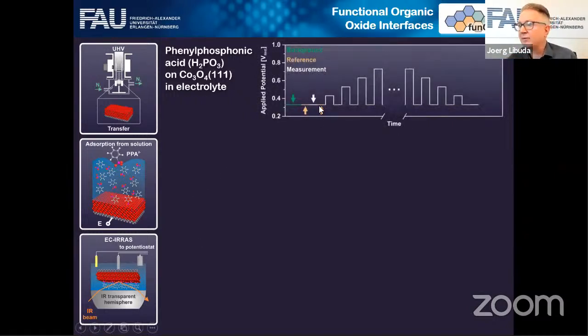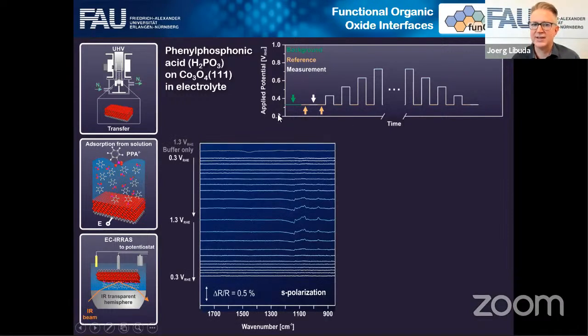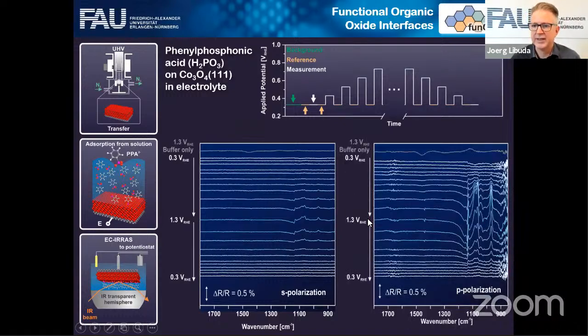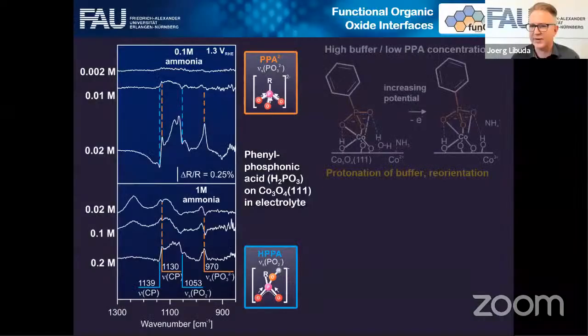And remember, infrared experiments are always difference experiments, as I said. So we have a reference potential. We jump to a different potential and go back and always do the steps and look at differences. And these are the difference spectra that you see in S-polarization. In S-polarization, you hardly see anything. It tells you that there's nothing going on in solution. That's good. Now the molecules don't dissolve, nothing going on. In P polarization, there's a very strong buffer as well.